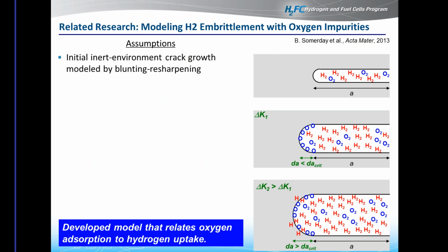So just to go briefly into the model, I only have a few slides left, but just to give you an idea how the model was come up with. If you imagine here in the upper right corner, we have a crack represented by length a, and we have a mixed species of oxygen and hydrogen. And we have to assume that this crack is going to grow just by regular inert environment crack growth mechanisms. So it's basically a series of blunting and resharpening, as we typically assume in fatigue. So that crack's going to advance slowly just through this amount, introducing new fresh surface, and then it becomes basically a competition for the oxygen or the hydrogen to adsorb onto the surface.